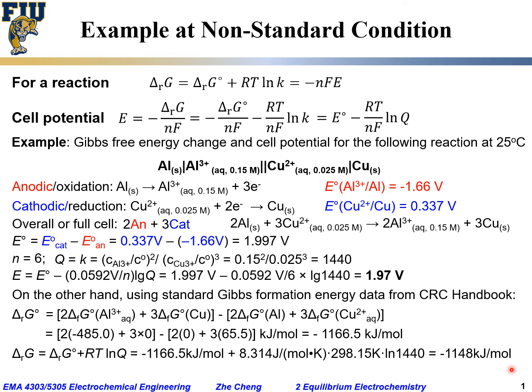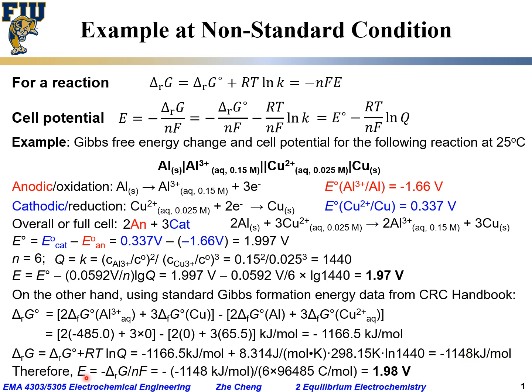Okay, anyway, with this ΔrG, the reaction free energy change value, we can calculate the cell potential. But remember, it doesn't equal 0 because the concentrations for the calculation are not under standard concentration. So E would just be minus ΔrG over nF. ΔrG is what we just calculated, minus 1148 kilojoule per mole, and n, similar to before, would be 6, and F is the Faraday constant, 96,485 coulomb per mole. You plug the numbers in, the calculated cell potential would be 1.98 volt.